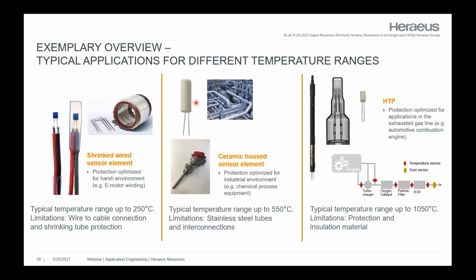Then you can switch to a different housing again, which is a ceramic tube filled with that ceramic paste, and you put in our sensor. You have to take care about bubbles and air holes like Charlotte described before. And if you make everything proper, make a nice connection, you can put it into a probe like that, and you have a good solution which works up to 550 degrees.